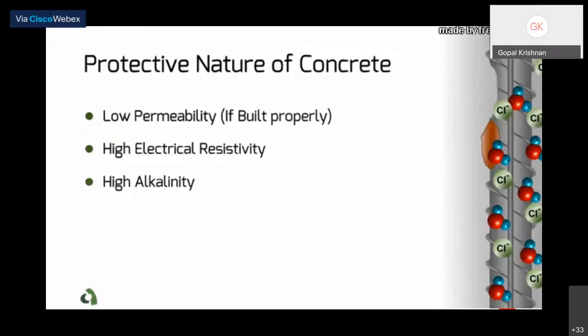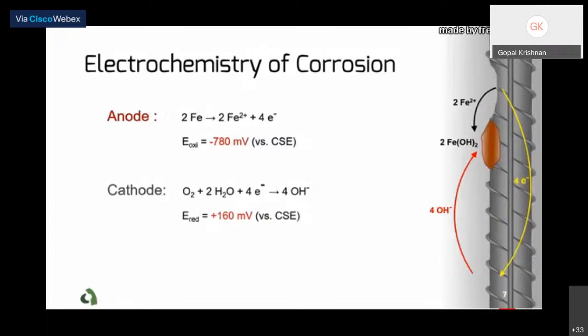As I mentioned earlier in this presentation, the porosity of concrete makes it possible for ions to penetrate into concrete and make the concrete itself act as an electrolyte. Corrosion happens in this environment, and the movement of electrons in concrete creates an electrical potential field inside concrete over the surface of rebar. For example, the reactions in the anode, where steel loses electrons, can create a potential difference of negative 780 millivolts compared to a standard copper sulfate electrode. The cathodic reactions would result in a potential difference of positive 160 millivolts.